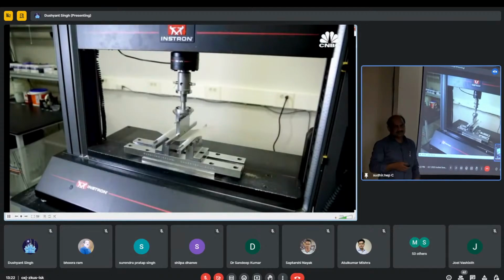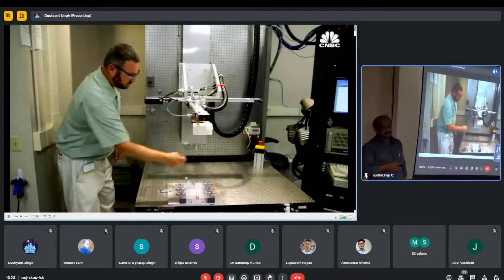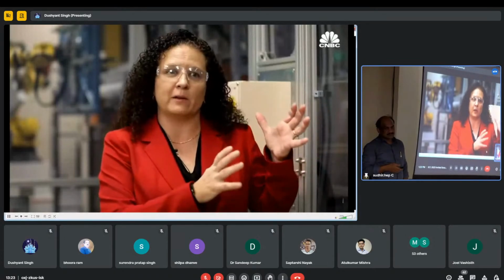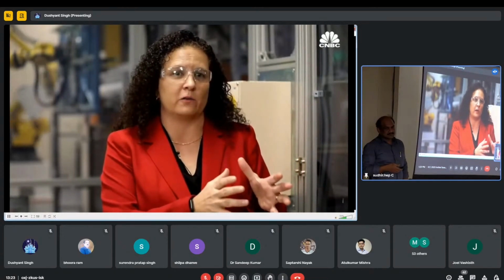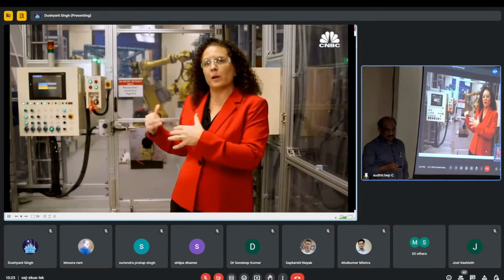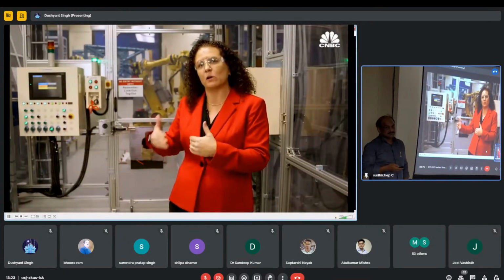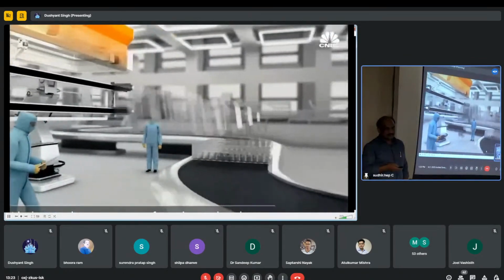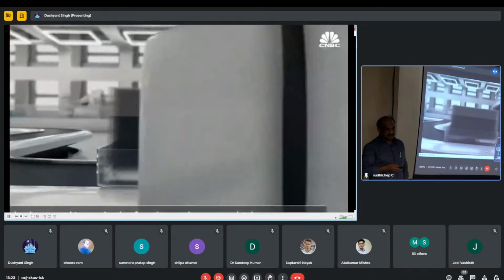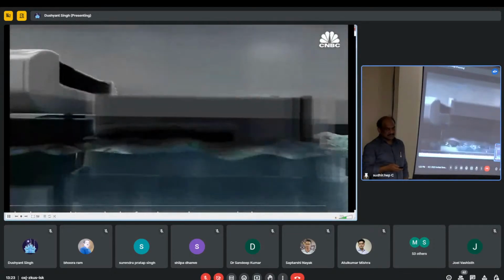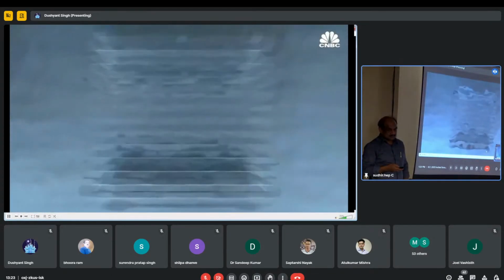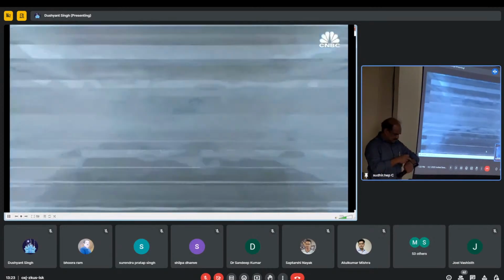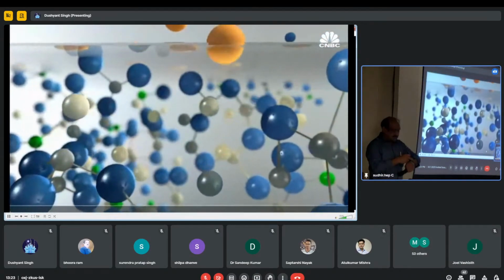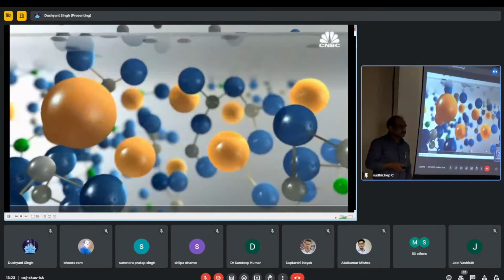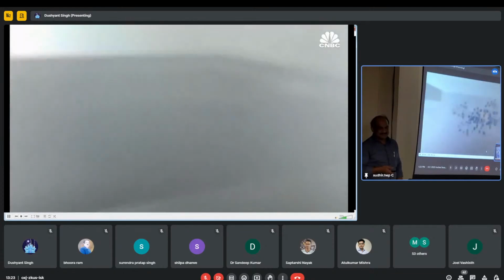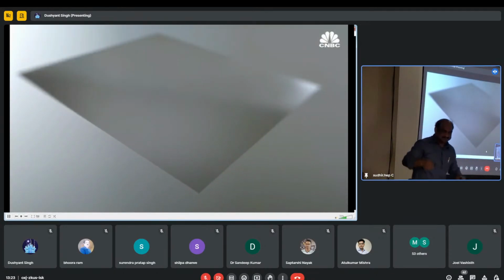Gorilla glass is one of the toughest glasses out there. And what makes it tough is not only what you see here, because it actually hasn't obtained all of its strength at this point. After it's packed and shipped, it goes through a chemical strengthening process called an ion exchange process. The composition that we set up allows us to take a finished sheet of glass, put it into a bath of hot salt, and in that bath of hot salt, sodium ions are exchanged for larger potassium ions in the glass. If you imagine those larger potassium ions packed into that glass, causing a much tighter and stronger compressive area on the glass.